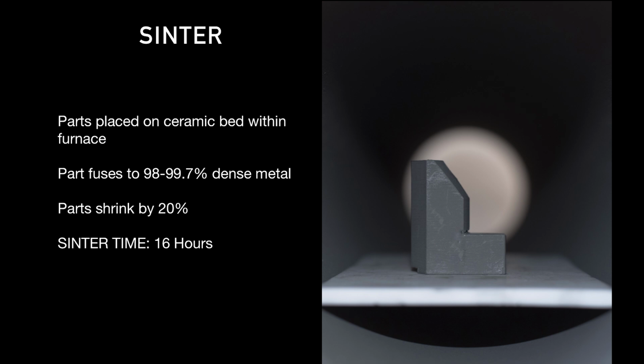for about 16 hours. During the sintering process, the part is run through a series of ramp and hold temperatures. The first hold temperature burns out the remaining binder material, leaving you with powder that is held loosely together. As you continue up the temperature ramp, those small metal powders start to neck into each other and then eventually sinter together, pulling into a part that shrinks by about 20%. And you're left with a final part that's fused up to